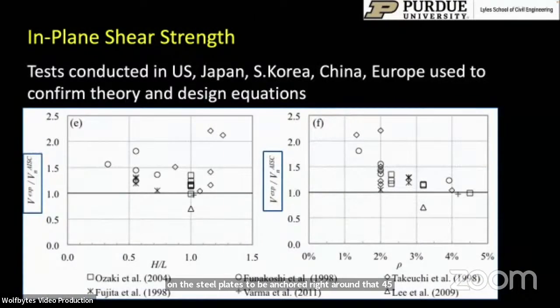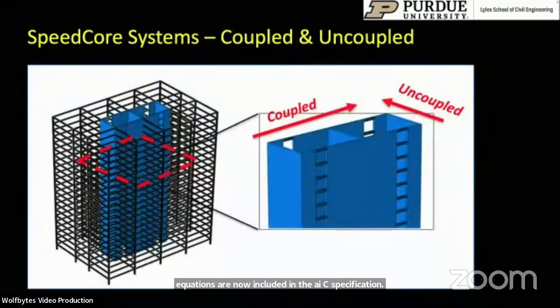Using this equation for the in-plane shear strength, we were able to collect all the experimental data from Japan, China, South Korea, and of course the United States. And we were able to develop a simple equation for conservatively estimating the in-plane shear strength of these walls. And these equations are now included in the AISC specification. And this is showing you the comparison of the experimental database with that.